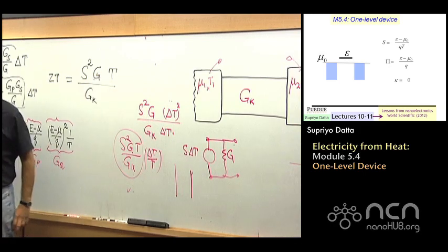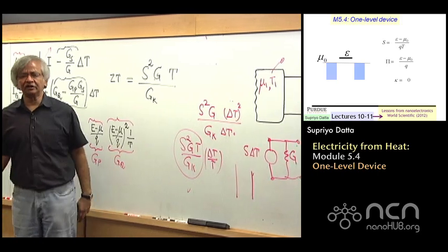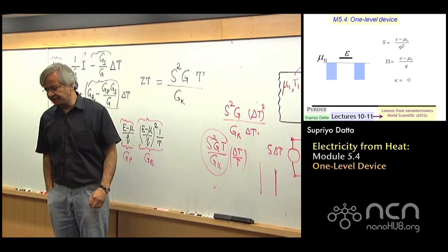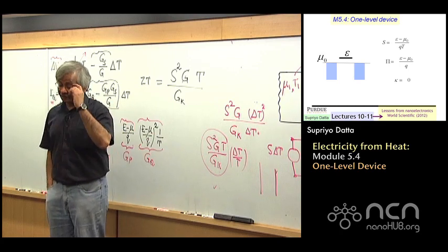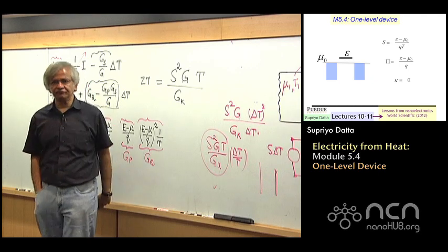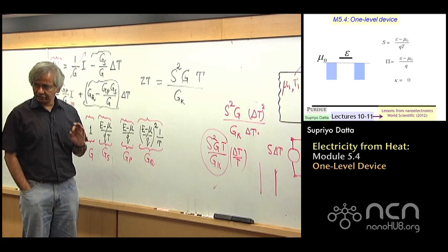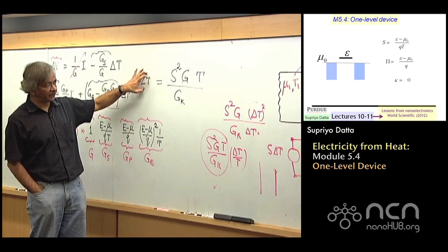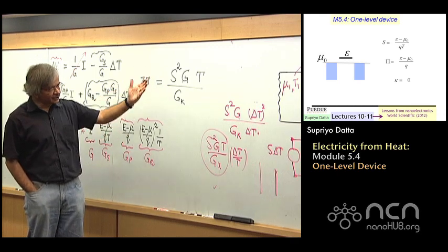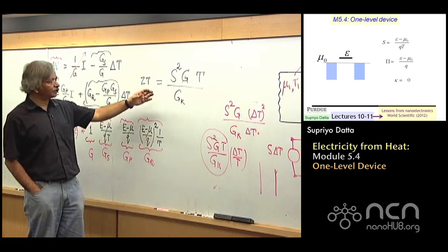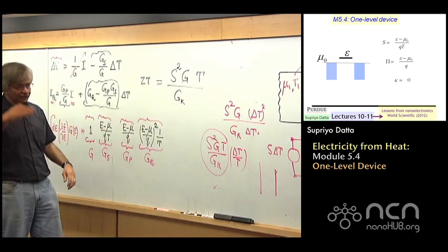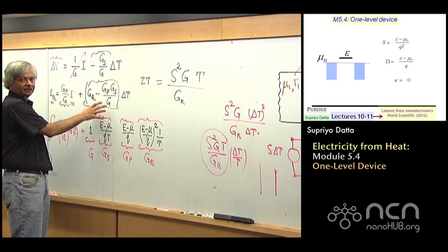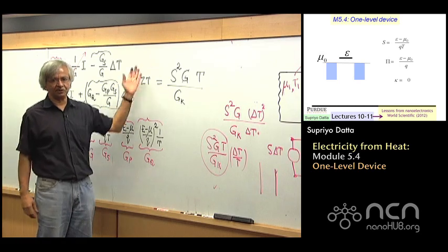And one of the problems with thermoelectric materials is that this ZT product for a long time has been stuck somewhere around one. People have been trying all kinds of materials trying to improve it. The understanding is that if instead of one, it could go up by a factor of three or four, it would make a whole host of different applications possible, which are currently not economically viable. But these could all become feasible if this number were bigger. And if you just looked at what we just discussed, you'd say the way to get good ZTs is to find materials with levels that are sharp. Because we just argued that a single level device has no heat conductivity. So you say, okay, I got a zero there, that should give me a huge number.